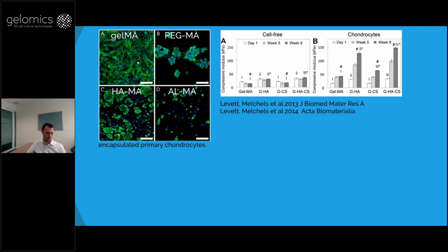The spreading is not a good thing for cartilage because it means it's dedifferentiated. We see they secrete collagen type 1, which is not the right type for cartilage. They did better in hyaluronic acid, where they stayed rounded and they made the right types of collagen and GAGs. So that's why we liked the fact that they proliferated in the Gelma. So we combined it afterwards in the second study, Gelma with HA, and found a good combination where we saw the cells proliferating as well as creating tissue of the right kind, the right GAGs and collagens.